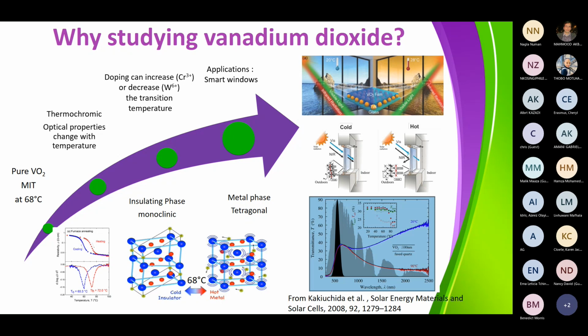And so that's very interesting, except that it's very rare that your window is going to be at 68 degrees Celsius. So you want to adjust the transition temperature to close to room temperature. And this is going to be efficient if you are able to do that.